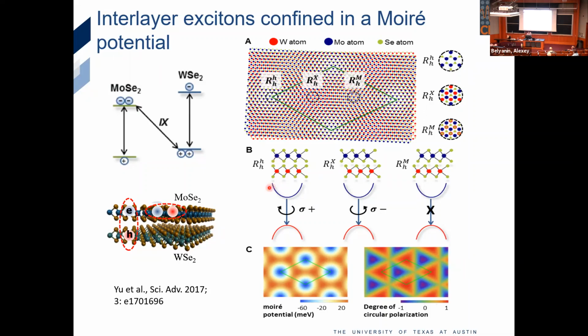This is just one valley. I still have the time reversal copy in the other valley, meaning that whenever I have a real space exciton here, I have a sigma plus transition in K valley. I also have a sigma minus transition in K prime valley. So it's a mess. Okay, so I have many transitions that are possible. To summarize, when I create a Moiré superlattice, I have this energy modulation, but now I also have this optical selection rule modulation in real space.